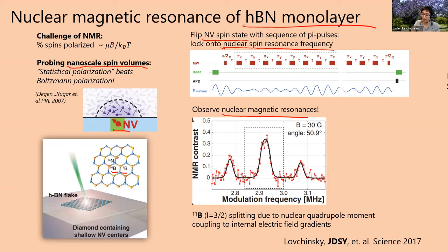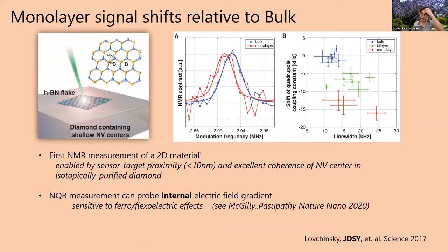Here you have a plot of NMR contrast as a function of frequency, and you can see these various transition lines that correspond to various nuclear spin transitions coming from the boron-11 atoms. So it's just NMR spectroscopy of these boron-11 atoms. What was kind of cute that we could do with this experiment is that we could measure the magnetic resonance frequency of these boron atoms inside the hBN and compare how it looks in the bulk versus a monolayer. You see here, the red is the monolayer hBN signal, and we see a clear shift in frequency compared to the bulk.